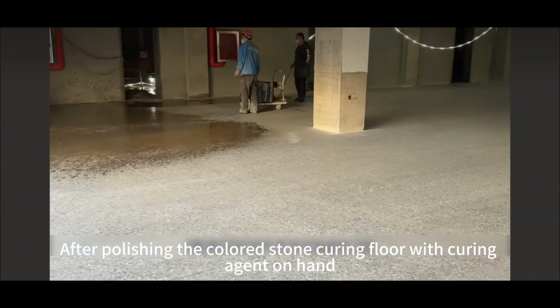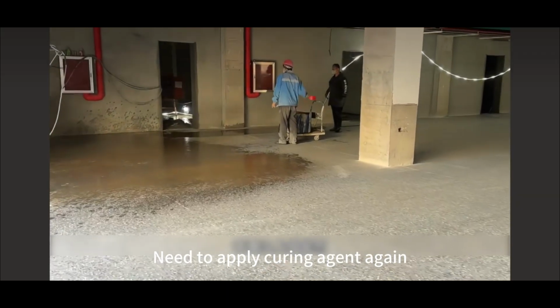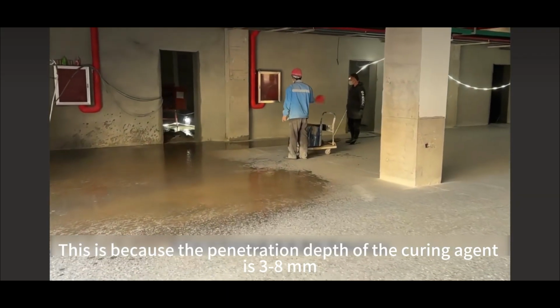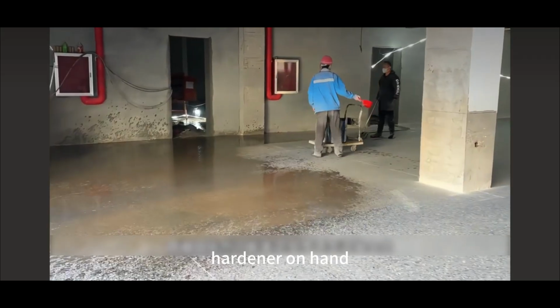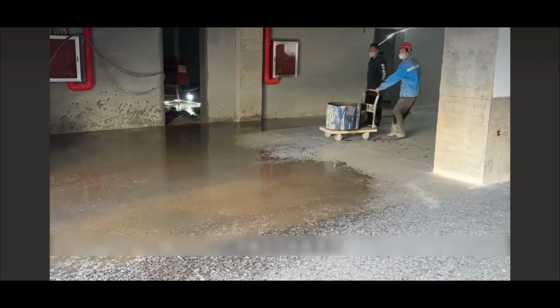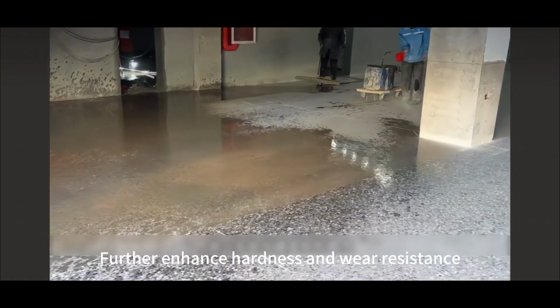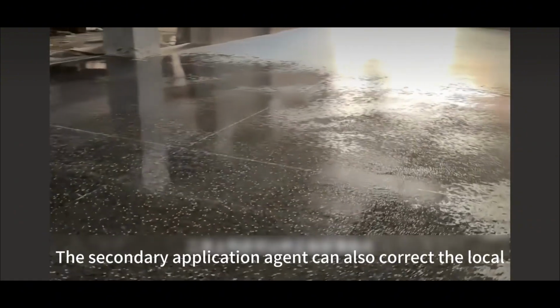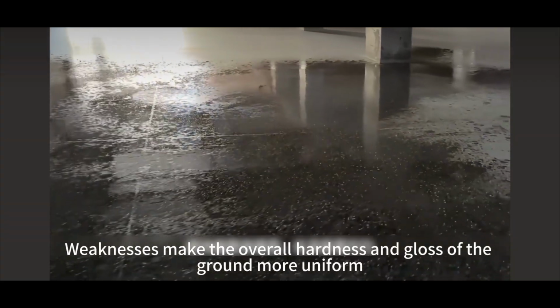After polishing the colored stone curing floor with curing agent, you need to apply curing agent again. This is because the penetration depth of the curing agent is 3 to 8 mm, so the first application may not fully penetrate into the concrete. Secondary construction can supplement infiltration, make sure the chemical reaction is fully carried out, and further enhance hardness and wear resistance. The secondary application can also correct weak spots, making the overall hardness and gloss of the ground more uniform.